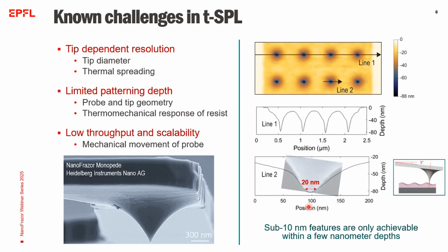And as demonstrated in our experiments, sub-10 nanometer features are only achievable within a few nanometer depths. And lastly, despite having similar speed to E-beam lithography in a few micrometer range, TSPL faces limitations in scalability because of the mechanical movement across large surfaces. And in our research, we focus on overcoming these challenges.